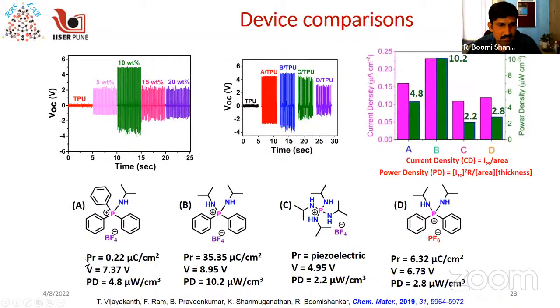We can see that as we measure different materials with different polarization values, different output voltages are generated. A material with the ferroelectric property gives higher output voltages in comparison with a material with only piezoelectric properties. And when we change from one anion to the other anion, there is also a change in the polarization as well as a change in the output voltage. So you can also calculate the power densities and current densities in the system, which will tell the efficiency of the materials.